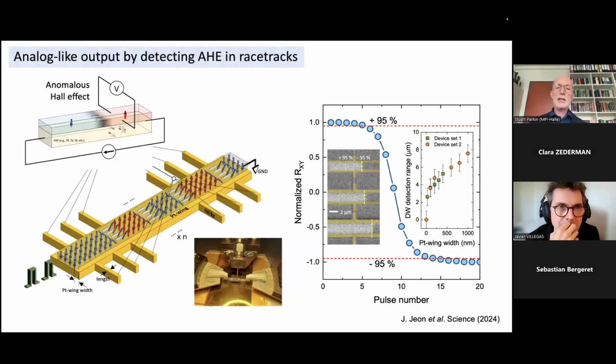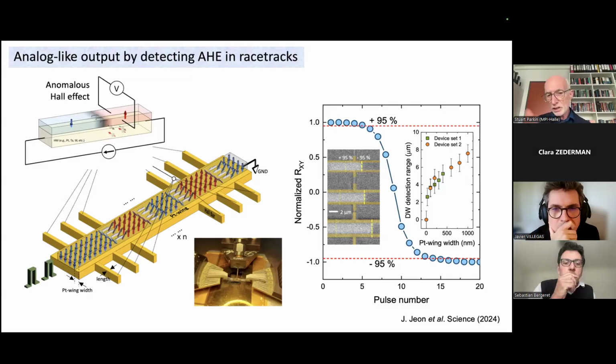So now I just wanted to finally mention that for the racetrack, of course, to make these racetracks useful technologically, they have to be very narrow, on the order of 50 nanometers or less wide. And we've been able to demonstrate the motion of domain walls through racetracks that are only 50 nanometers wide by building this racetrack.